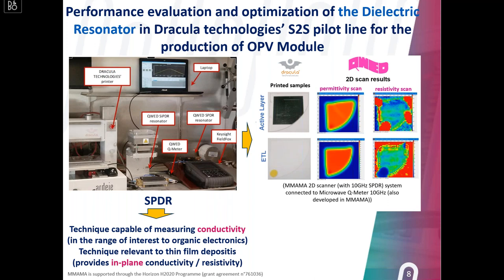What is very important in these 2D scan images is that the resistivity of the printed layer is not uniform over the total surface, which for us is not a good indication. As mentioned before, to guarantee the performance, we should develop uniform layers. And if the resistivity is not uniform, it means the thickness is not uniform, but it can also mean we have some impurity or some other problem inside the bulk. This is why this technique can give us information about the homogeneity of the layer, and is able to distinguish whether the layer is homogeneous or not.